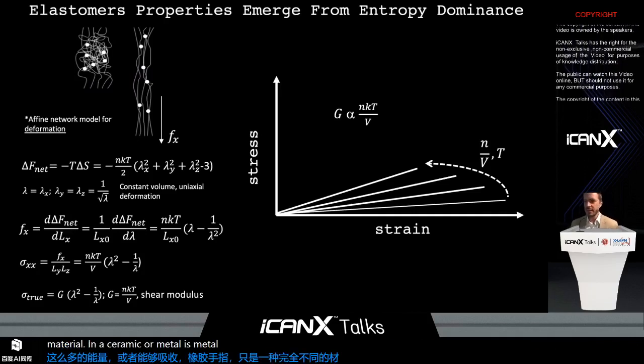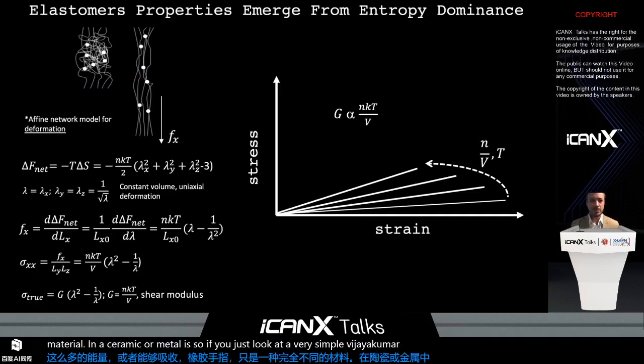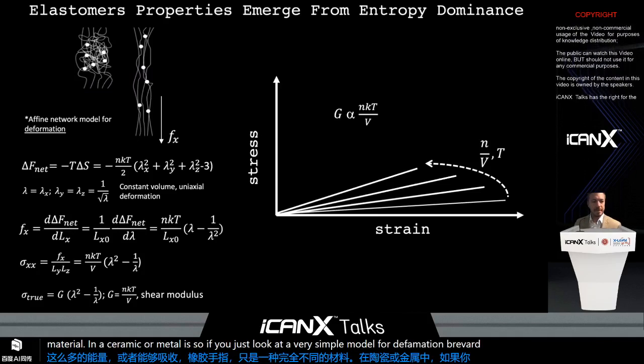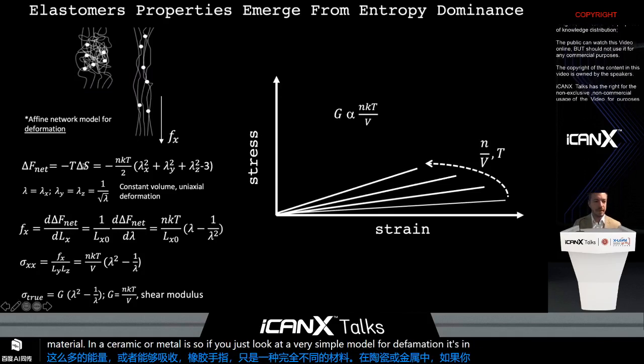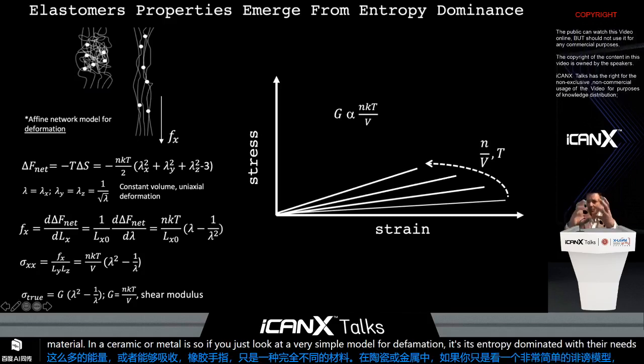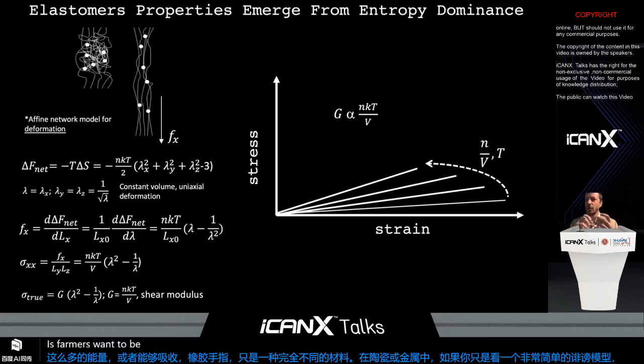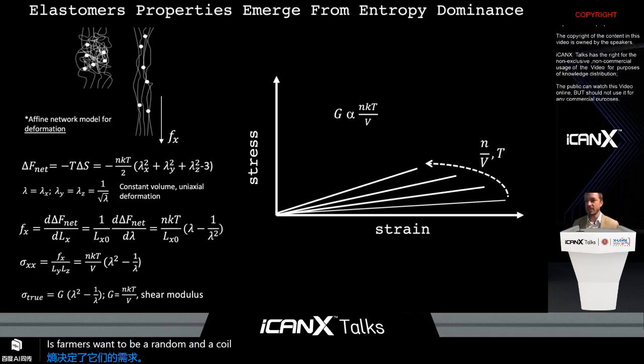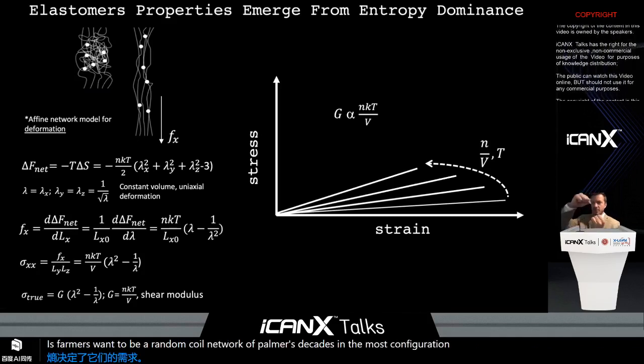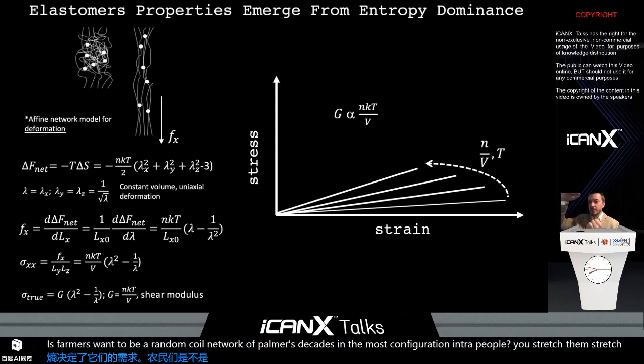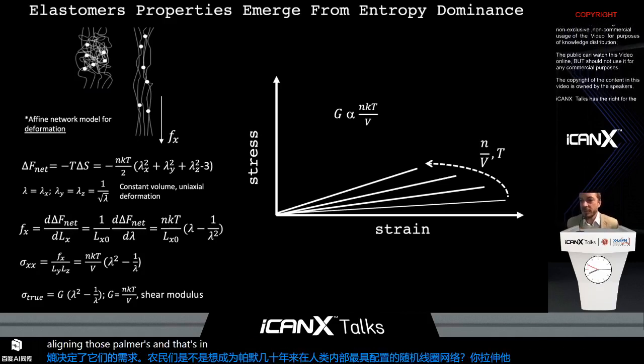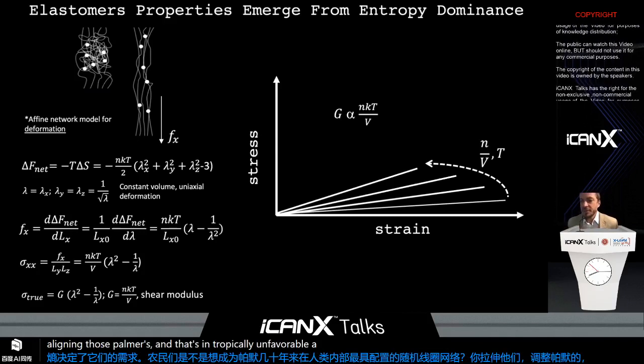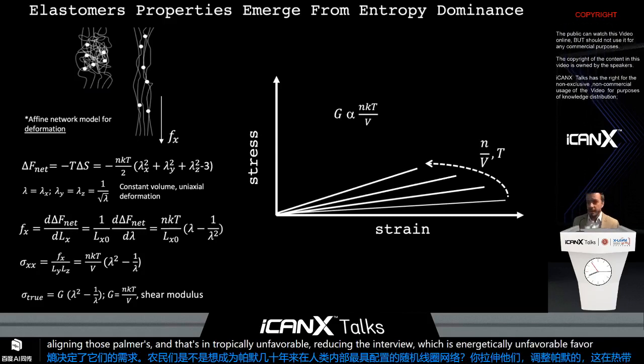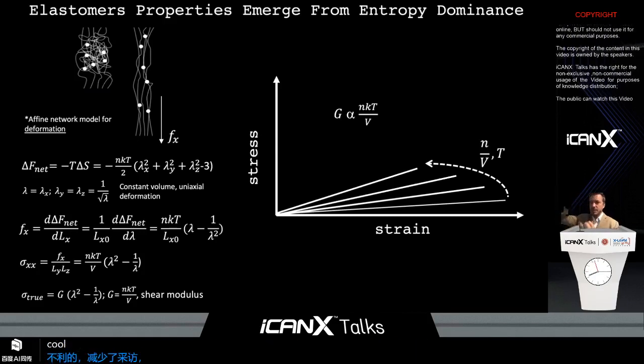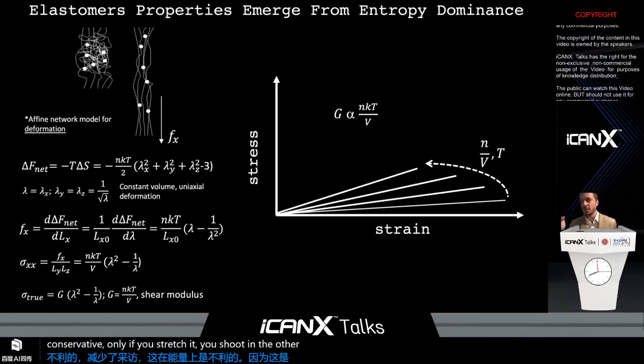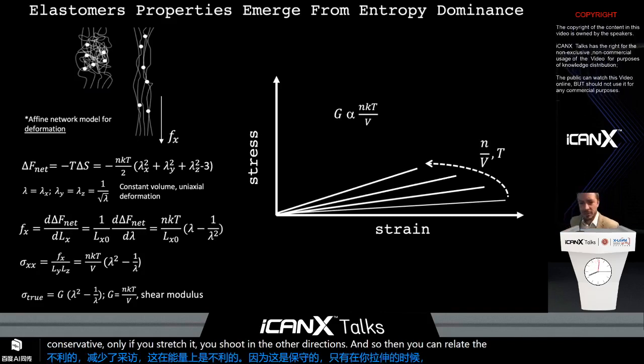So if you just look at a very simple model for rubber deformation, it's entropy dominated. And what that means is polymers want to be a random and coiled network of polymers. That gives them the most configurational entropy. But when you stretch them, you're aligning those polymers, and that's entropically unfavorable. Well, it reduces the entropy, which is energetically unfavorable. And since this is a conserved volume, when you stretch it, you shrink in the other directions. And so then you can relate these principal strains to each other.